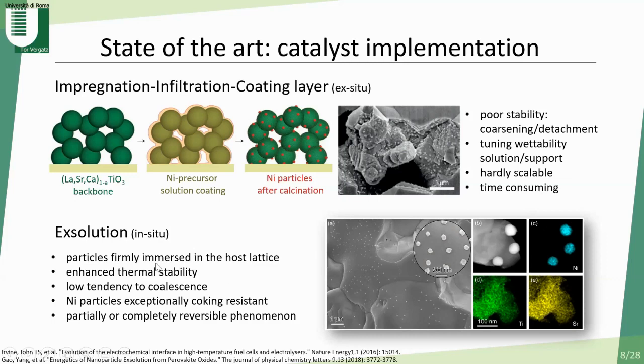Catalytically active transition metals are substituted in the B site of the perovskite oxide in oxidizing conditions and released on the surface as metal particles once the oxide lattice has been reduced. Exsolved particles are about 1/3 immersed in the surface of the host lattice and possess enhanced thermal stability and low tendency to coalesce.